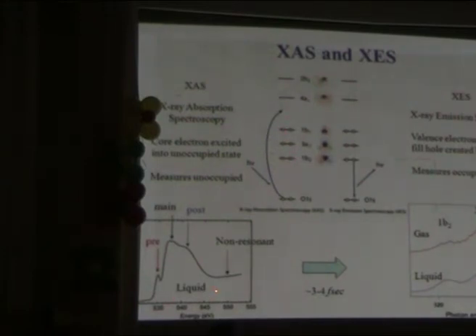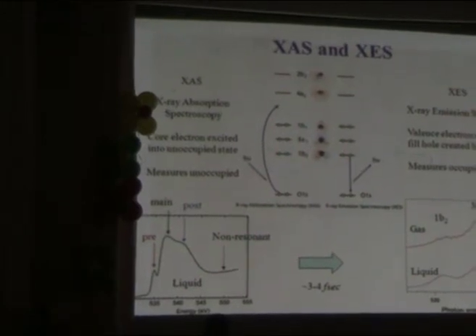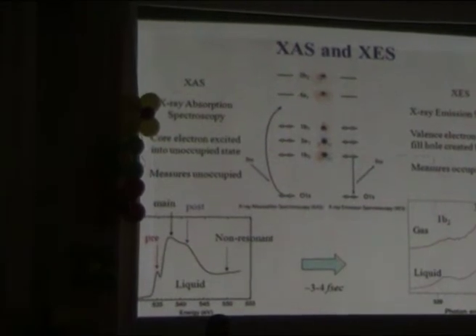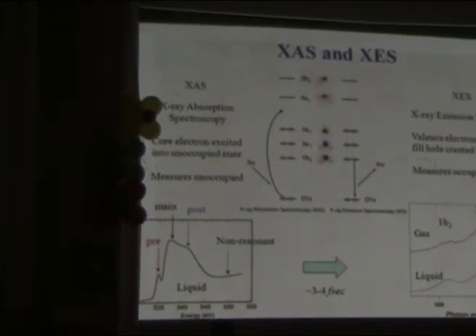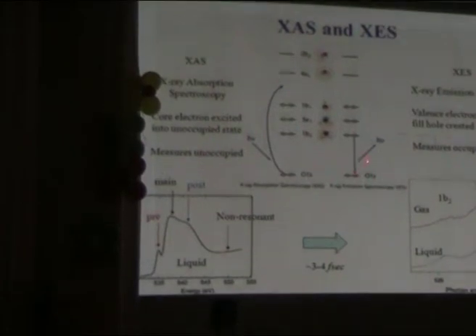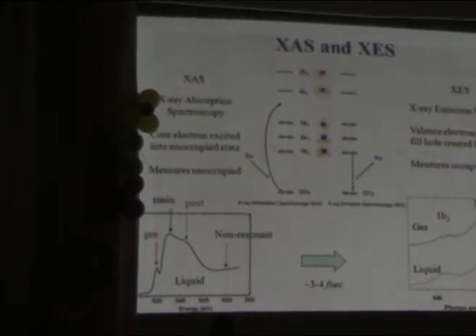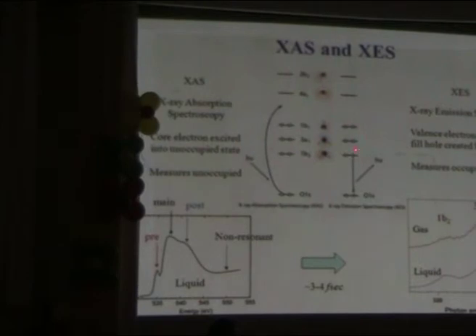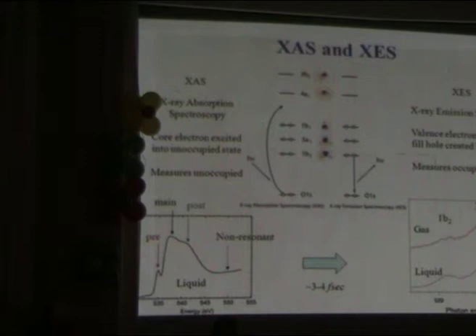It's a very high energy, of the order of 540 electron volts. So it's a highly excited state, which means that it has a short lifetime. Then we get a decay. The dominating channel is, of course, Auger decay, but a minority channel is fluorescence. Then we get an X-ray photon out that can be detected. That gives us a direct measurement of the energy difference between the valence states and the core level.